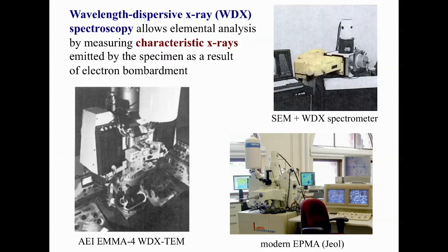Fortunately, there is an alternative to electron spectroscopy, namely the spectroscopy of X-rays that are emitted when energetic electrons enter a solid specimen. In the 1960s, wavelength-dispersive spectrometers were added to a TEM, or an SEM, and there is still an instrument known as the Electron Probe Microanalyzer that uses WDX technology to measure elemental concentrations down to parts per million in favorable cases. The wavelength-dispersive spectrometer has good spectral resolution, but is inefficient because it has to scan through each X-ray wavelength in turn. If we want really good spatial resolution, the specimen must be thin, and WDX measurements then take a long time.